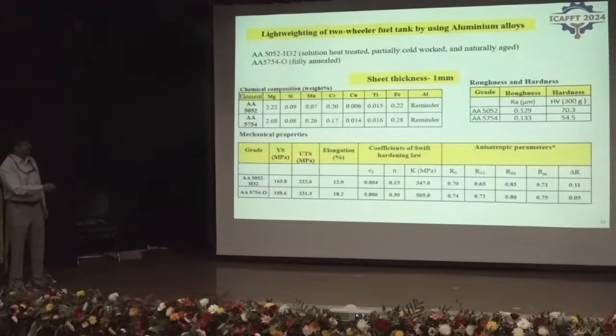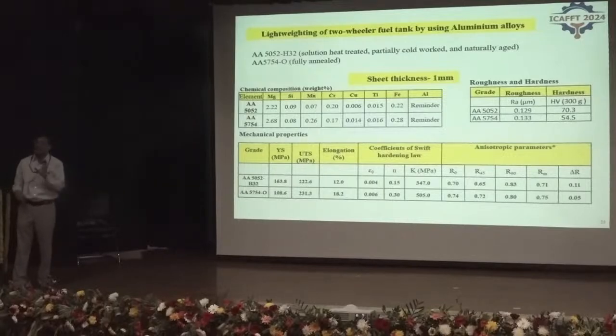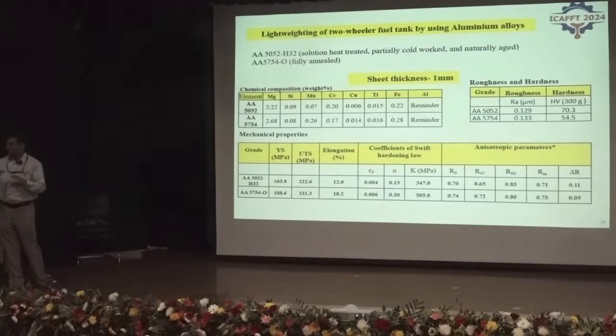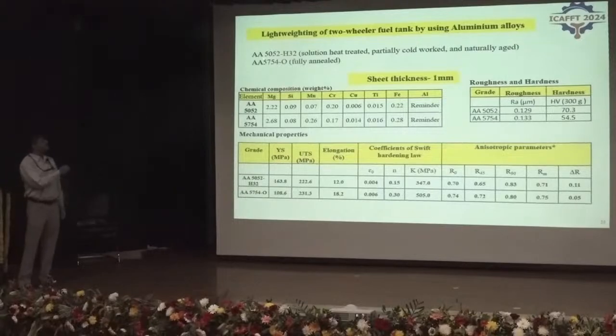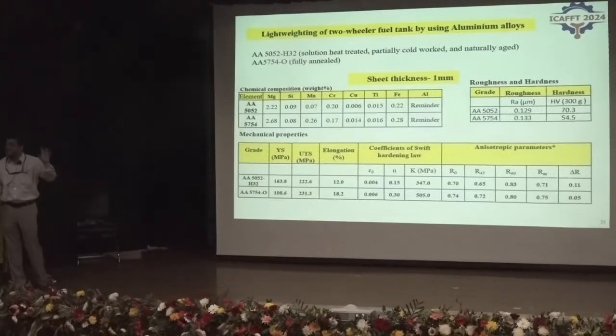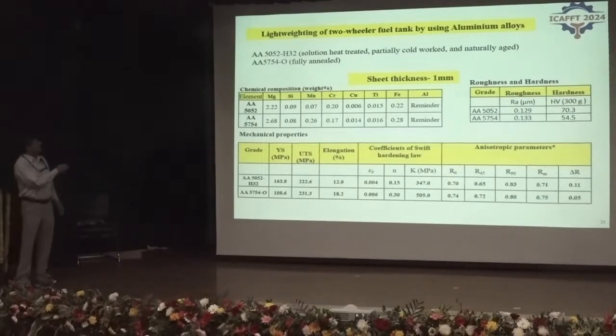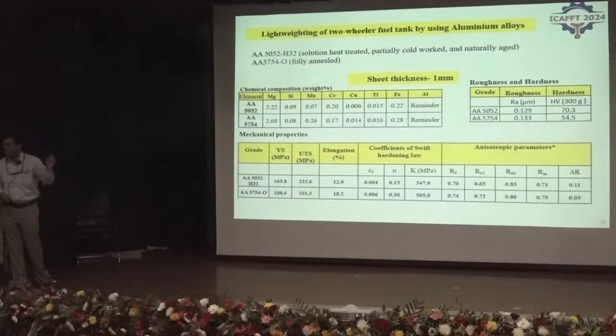And the next alternative is to use aluminum alloys in place of steel. So we have chosen two aluminum alloys, both belonging to 5000 series, because 5000 series belongs to work hardening alloys. They have very high work hardening ability. 5052 has been chosen because that is being presently used in two-wheeler industry for a few other sheet metal parts. And in the annealed condition, it has very low strength. So therefore, we used it in the solution treated, partially cold worked and naturally aged condition. That is H32. That's the most common temper in which this sheet is used.